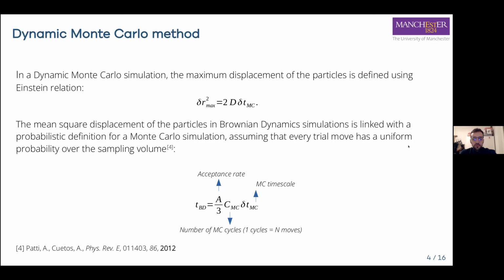To investigate the diffusion of these particles with an anisotropic shape interacting with hardcore interaction, we perform these dynamic Monte Carlo simulations. In the frame of dynamic Monte Carlo methods, we first need to define the maximum displacement and rotation of the particle using the Einstein relation. So the maximum displacement of the particles and their maximum rotation is defined by a Monte Carlo time scale, which is unique to the particle shape. It also depends on their translational and rotational diffusion coefficients at infinite dilution. And we can recover the proper time scale from the Monte Carlo simulation, linking the mean